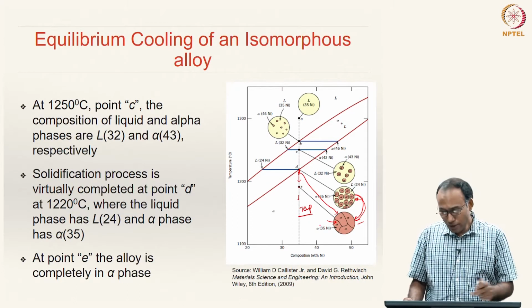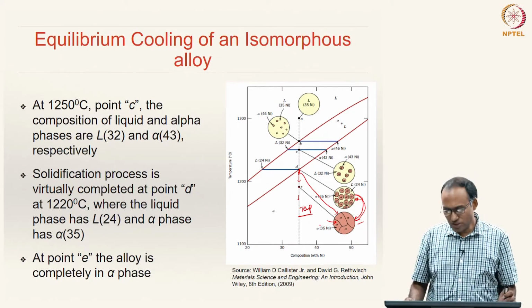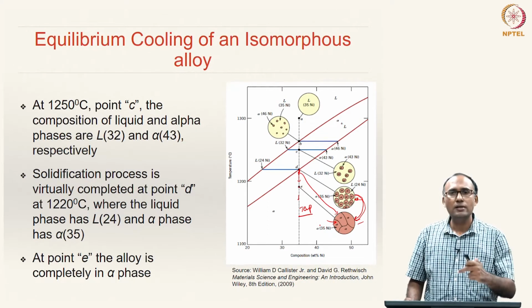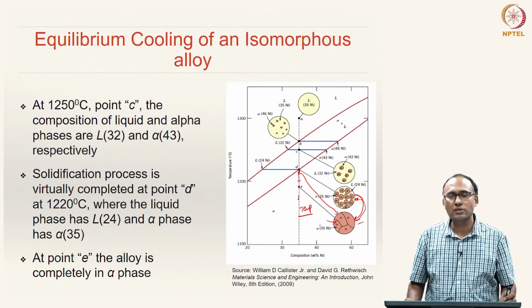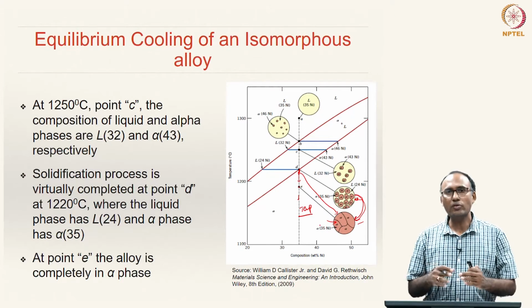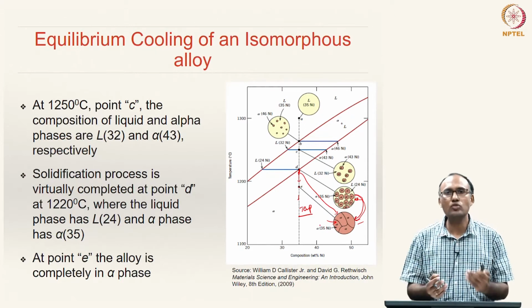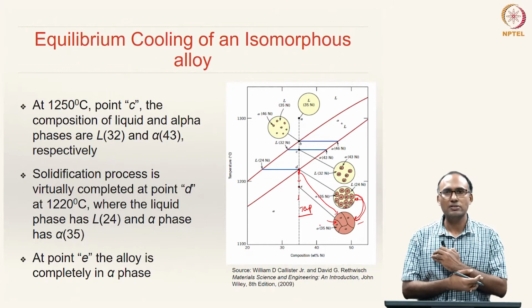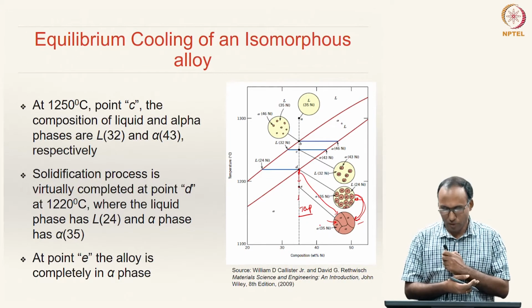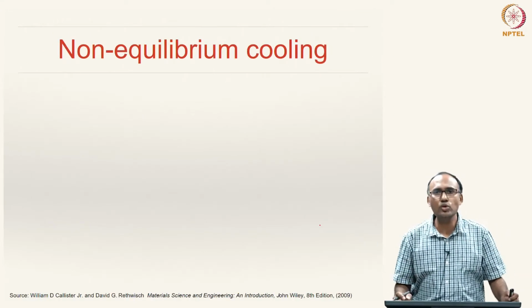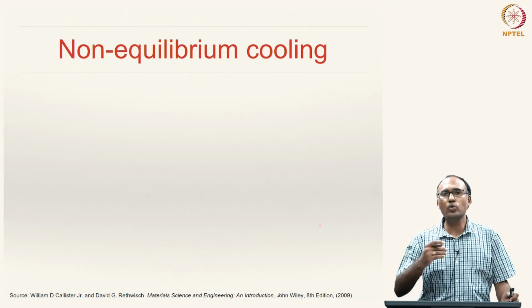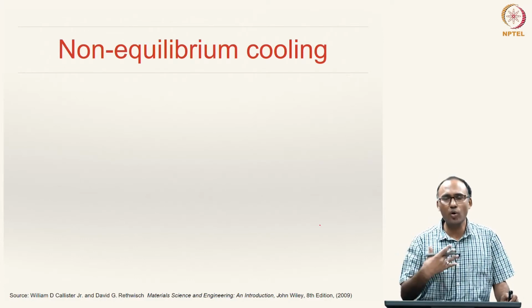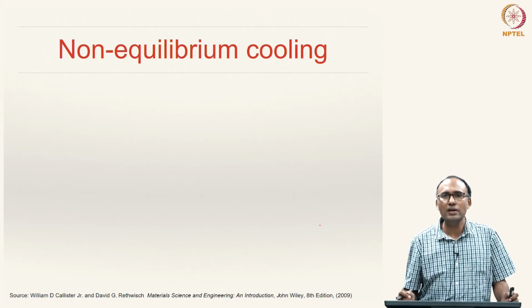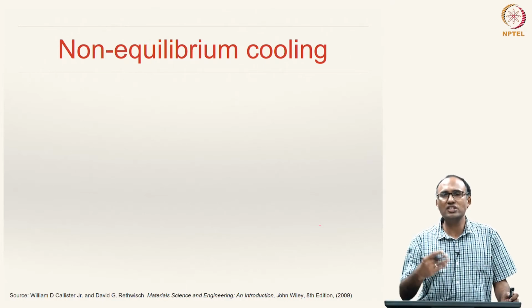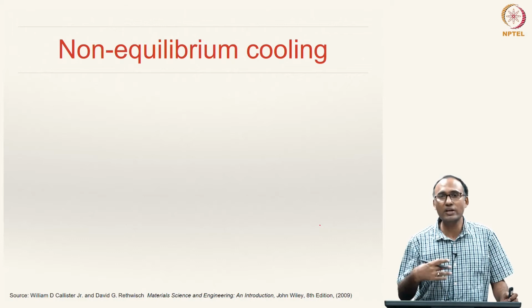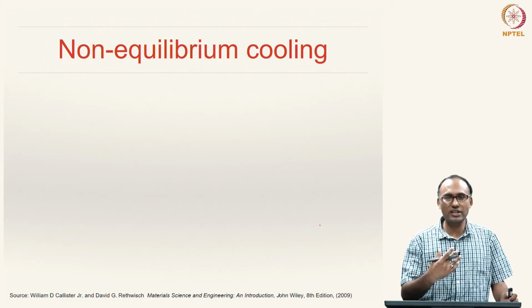All right, and when we are drawing these microstructures, the assumption is that the cooling is done in an equilibrium manner, meaning we have done the cooling at a sufficiently slow rate. That means the cooling rate is very, very low. Okay. So, what happens if you do non-equilibrium cooling? That means if your cooling rate is not as slow as what we have shown here, the system does not reach its equilibrium configuration. If the cooling rate is high, the system does not reach its equilibrium configuration.